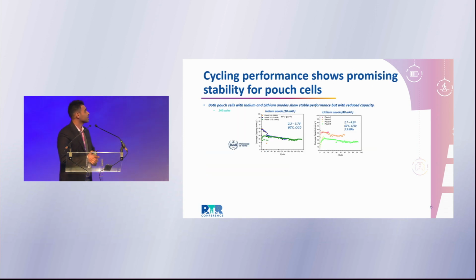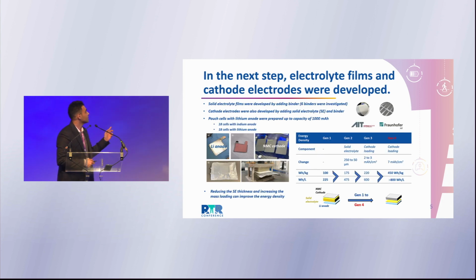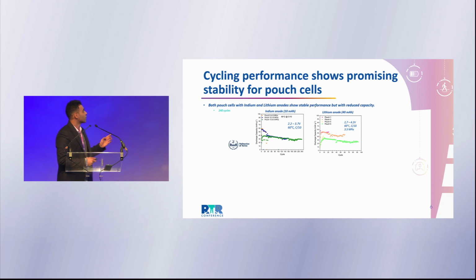Then we tested the cell. So we made, if you want to slide back, we made 18 cells with indium anode, 18 cells with lithium anode, and then we tested the cells. So for testing, these are the cells with indium anode and lithium anode. You can see both of them. The cycling performance is stable.